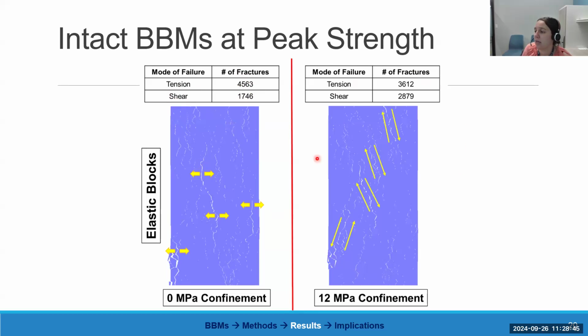On the other hand, on the right here, we've got the higher confinement case. You'll see that the number of tensile fractures has come down and the number of shear fractures has come up. And we still have a lot of axially oriented tensile fractures at this point, but they're not coalescing as much. We've got this en echelon stair-stepping pattern and a bit more global shearing than we did in the lower confinement model. And so it's higher confinement, it's not super high confinement. So this is what we'd expect.